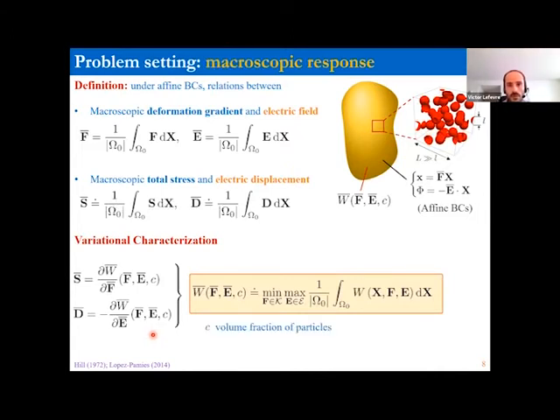So here I've introduced c, the volume fraction of particles. It's going to be important in a second. And just to make sure that we're not doing anything fancy when solving this variational problem, the two Euler-Lagrange equations associated with this problem are nothing but balance of linear momentum and Gauss's law, which are the two governing equations that eventually we need to satisfy in the material. So that's the problem that we want to solve. Once you know the W bar, you can use these partial derivatives and you have the constitutive behavior of the composites. And so the name of the game is computing solutions for W bar for different families of composites, and that's what I'm going to show you.